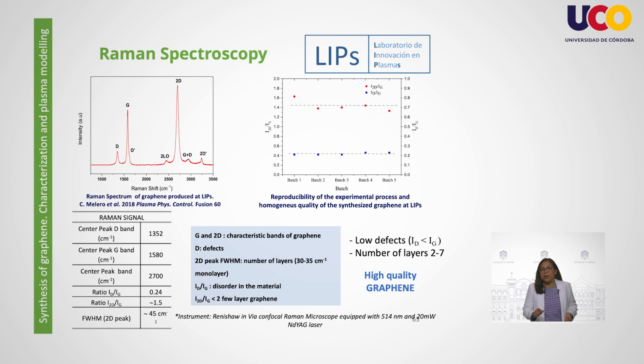In Raman spectroscopy for graphene, there are three main response peaks to observe: the D, the G, and the 2D. The G band appearing at 1580 cm^-1 corresponds to the plane configuration of carbon atoms bonded with sp2 hybridization. This location of the G peak discards the presence of graphene oxide, which is slightly upshifted to 1594.